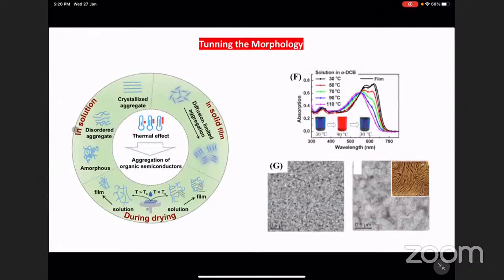You use this knowledge, and what you do is take a system, heat it up, and then cool it down. When you heat it up and cool it down, what was initially aggregated, you have made amorphous, and then these disordered aggregates are used to make the films. During the drying process, all these phenomena take place, and at the end of the day, what you get is very long-range ordered fibril structures. If you don't do this cold, hot, cold, and directly use a hot solution to spin cast, you don't get those fibril structures, which are shown here. This is the TEM image at the 0.5 micrometer length scale, and these are the AFM images. You see these very nice polymer fibers, and that explains lots of things.